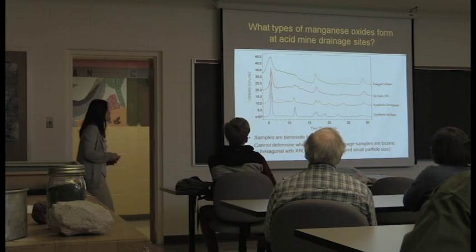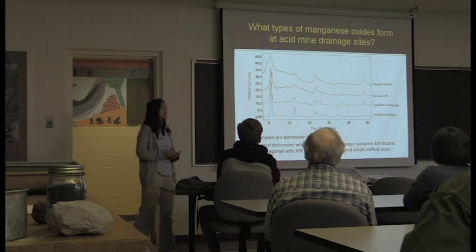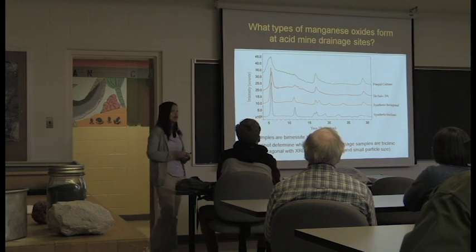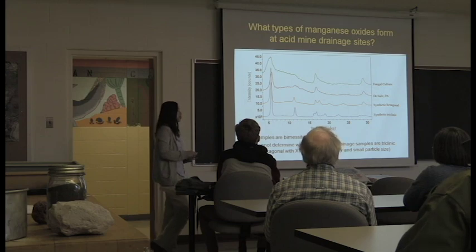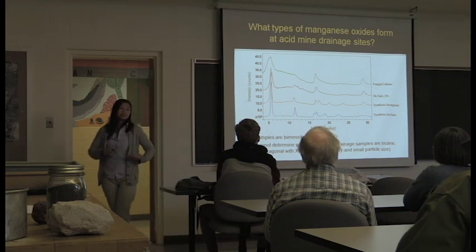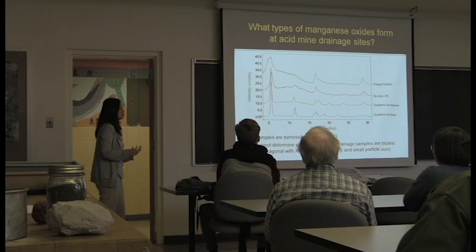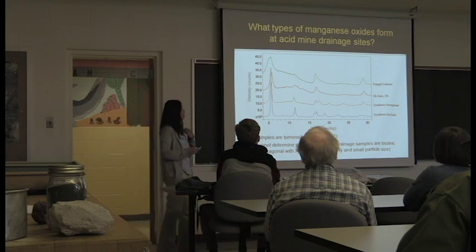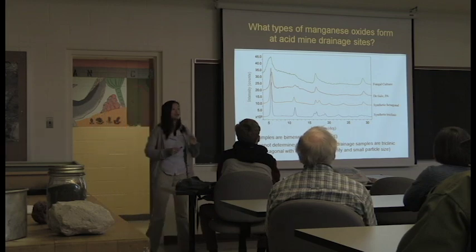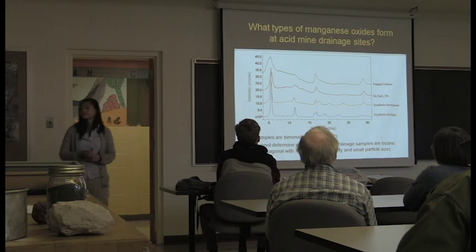And this is because the manganese oxides that we're finding at our acid mine drainage remediation sites are really poorly crystalline and very small in particle size. And when you think about XRD, what we needed was a nice crystal structure in order to allow the X-rays to diffract. And we don't have that in a poorly crystalline structure.